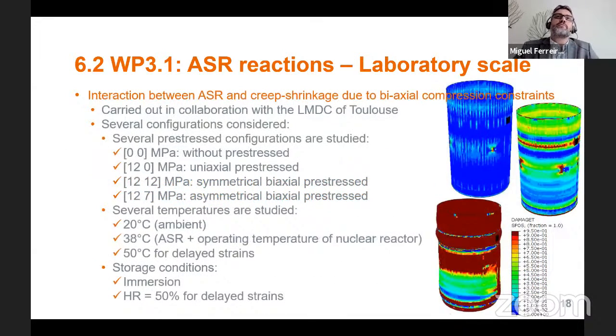So here are some of the variables that we are dealing with. Different types of pre-stressing. So we'll have samples that are not pre-stressed, samples that are uniaxially pre-stressed, samples that are symmetrically biaxially pre-stressed, and samples that are asymmetrically biaxially pre-stressed. And if you look at temperature and humidity conditions for the ASR samples, they'll be placed in water at 38 degrees. But if we're looking at delayed strains, these are kept at 50% relative humidity and are stored at 20, at 38, and at 50 degrees. So at 3 different conditions, and these reflect different temperatures that can be found at nuclear power plants, different working conditions. And 3 different concrete mixtures will be used as well.